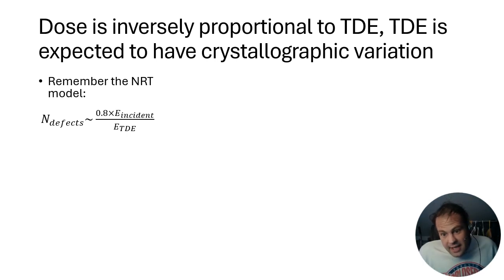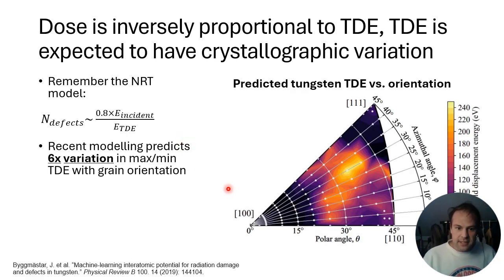Now, I said this TDE is a material property, so is there anything that we can do to exploit materials in order to make a more radiation tolerant component for a reactor? Now, we think back to this NRT model that we've got: our dose is inversely proportional to threshold displacement energy. And we look to these recent modeling results in tungsten, where they've used a machine learning informed interatomic potential to make this very fine 5-degree increment map through crystallographic space in all these different possible crystal orientation directions. The threshold displacement energy is calculated by molecular dynamics, and it's predicted that in the 3-2-1 direction, the threshold displacement energy might be 6 times higher than it is in the principal directions.